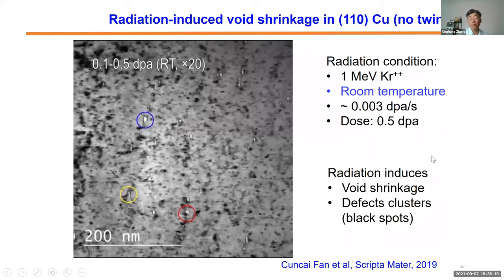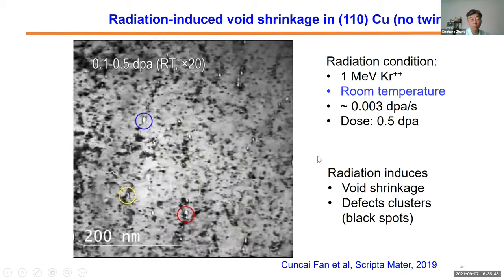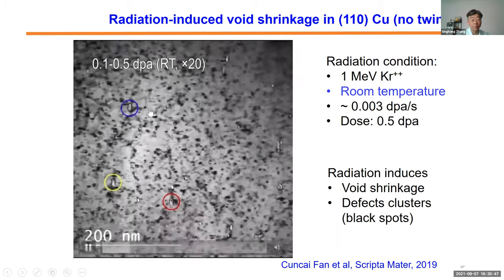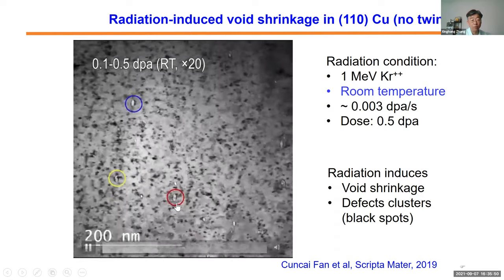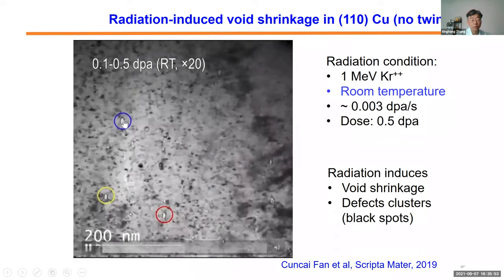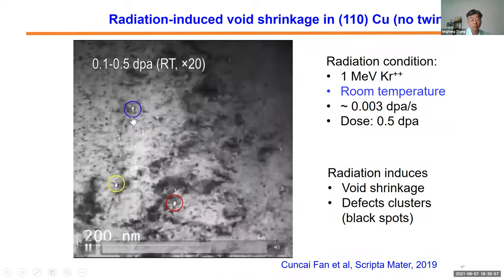And then you might say, what if you simplify the scenario? You remove twin boundaries. You look at just nano voids by themselves, what's going to happen? So this is the example where we look at copper, not the 111 nano-twinned copper. Instead, it's 110. So when you have 110 single crystal copper films, there are no twin boundaries, but we still have these voids introduced in the as-deposited film. And now if we perform the same radiation experiments, again at room temperature, and the video was accelerated 20 times, look at the blue, yellow, and red circles, and you find these voids actually all shrink as well in the room temperature radiation experiment.